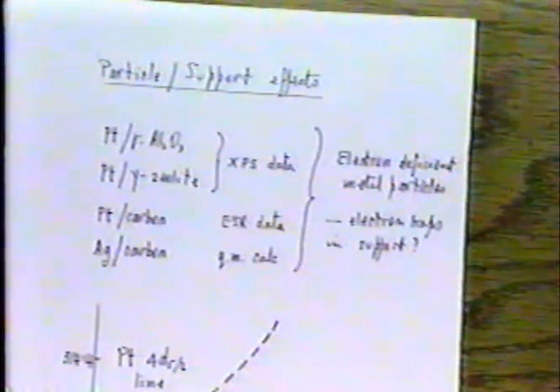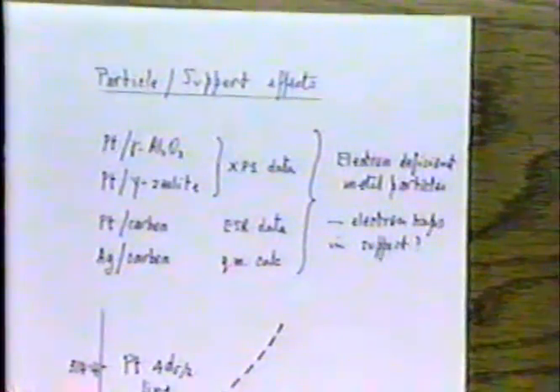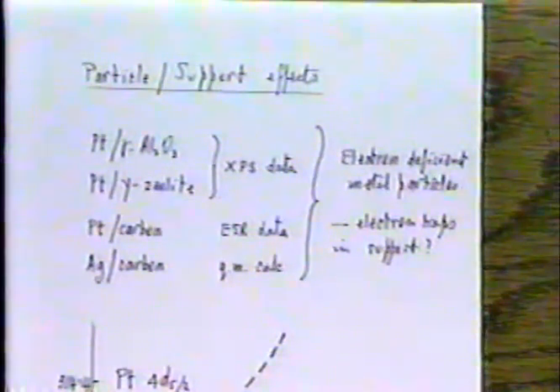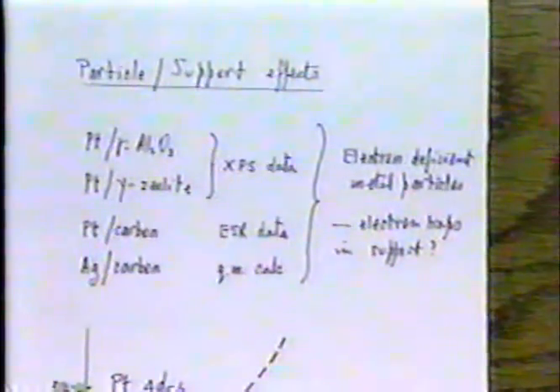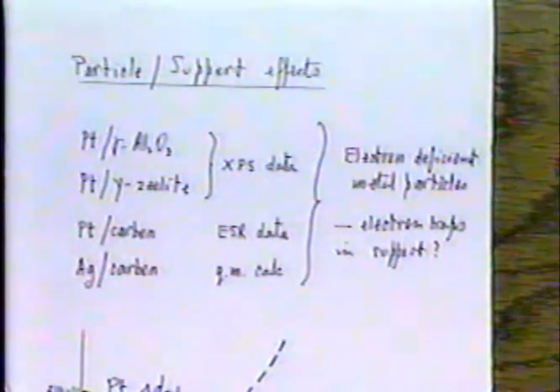Generally speaking, small particles of the size 20-odd angstroms and less cannot exist by themselves. They have to be sitting on a support. And if they are sitting on a support, what effect does the presence of the support have on their electronic properties, if any? And the answer is, in general, it does have an effect. The support does have an effect, but the nature of the effect is fairly strongly dependent on the chemical identity of the support itself.